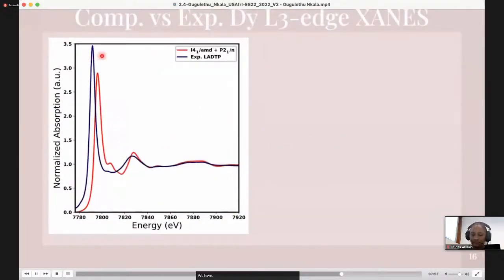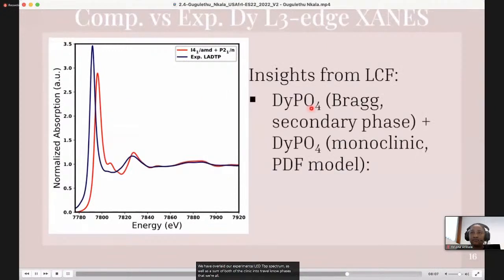We have overlaid our experimental LADTP spectrum as well as a sum of both of the monoclinic and tetragonal phases that were obtained from Bragg data as well as the PDF. Using only the tetragonal phase from Bragg data showed a significant discrepancy in the higher energy range, suggesting that this model could not fully describe what we observed experimentally.